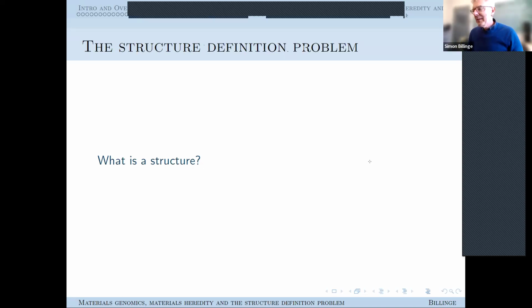If you ask a chemist, they'll talk about an FCC structure, and they'll say that's a structure. But you can have iron as a FCC iron, and you can have FCC nickel. But according to Vitaly, FCC nickel and FCC iron are different structures because they have different interatomic distances. But according to the chemists, those two things have the same structure. So there's an ambiguity in what we mean by structure.